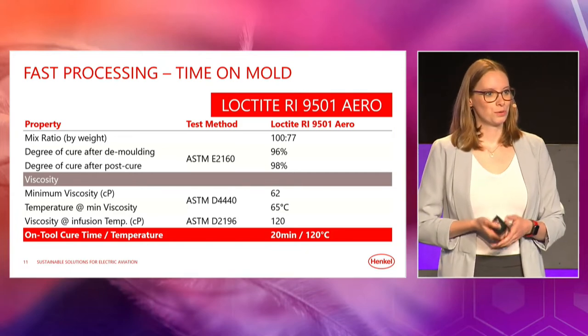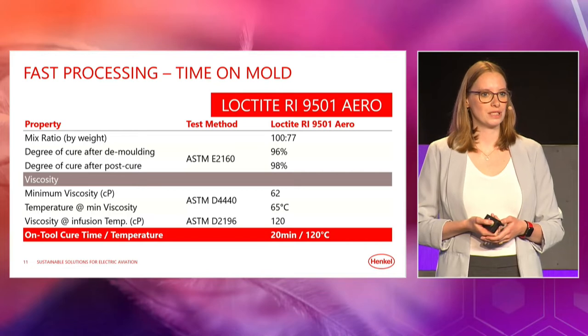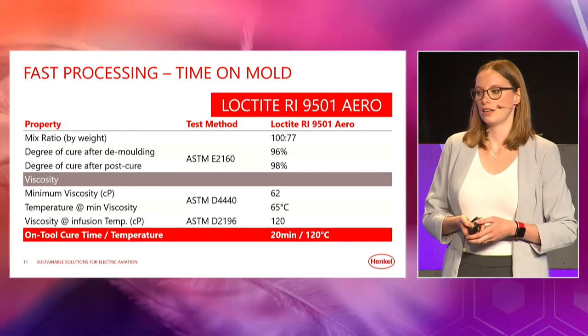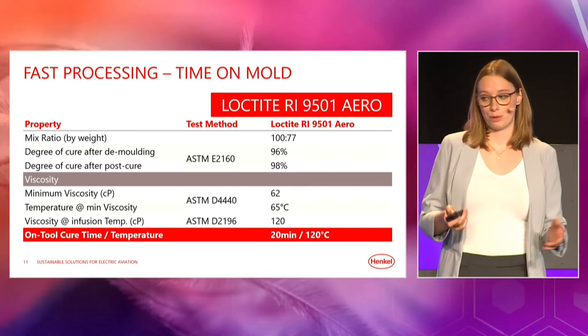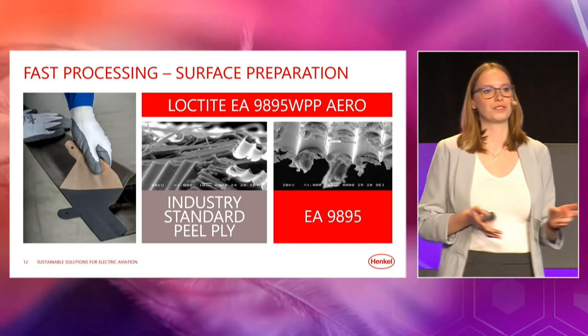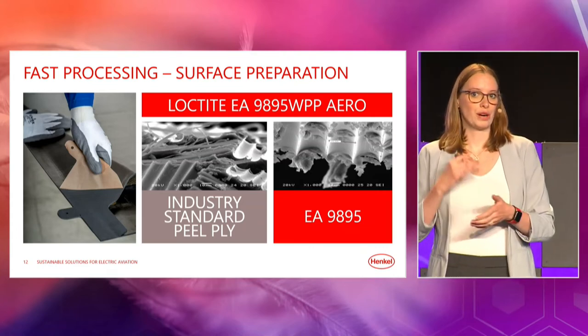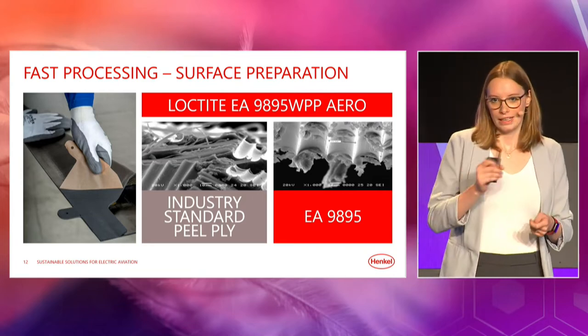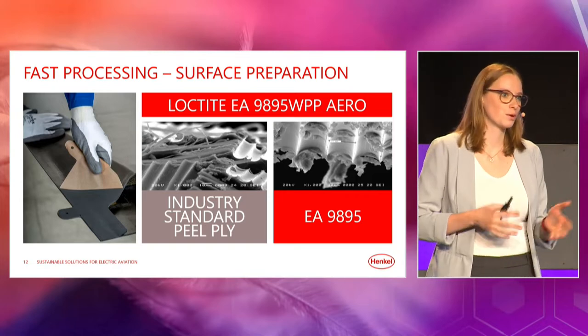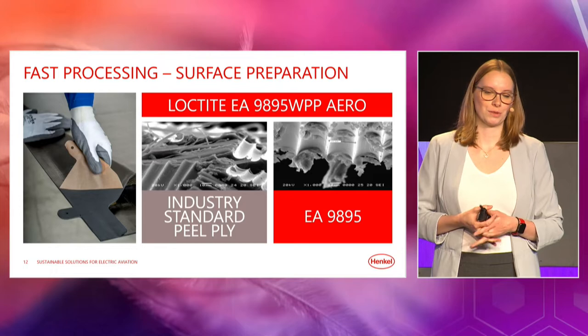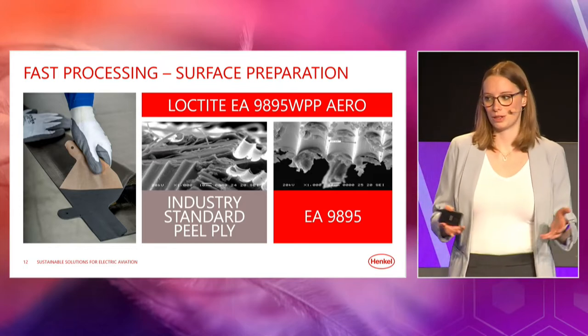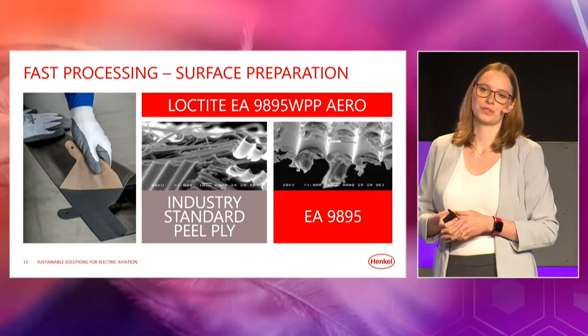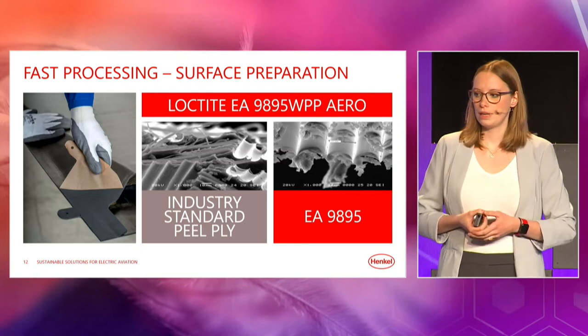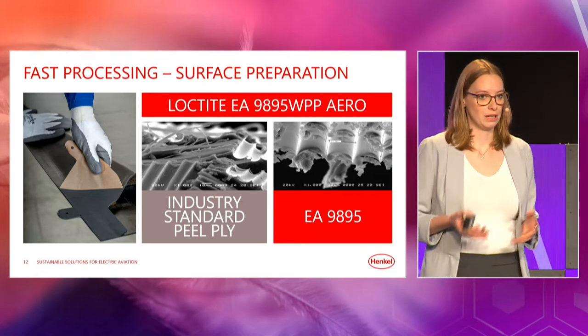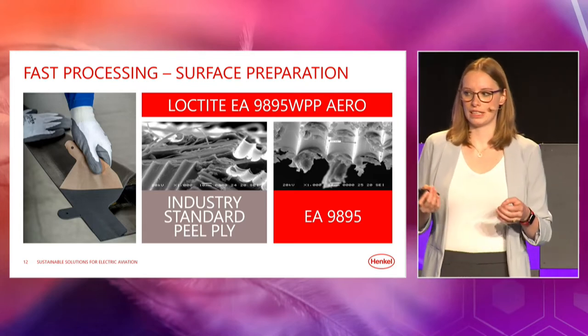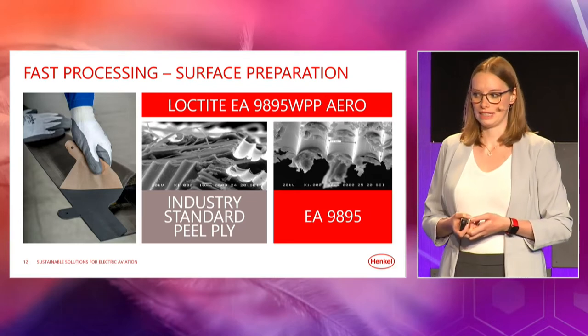As we are now able to produce composite components in RTM processes 4 to 5 times quicker than the standard process, we need to be quicker at surface preparation as well. And here we have two different processes we can use. One is abrading the surface manually, so abrasion by hand, and this of course comes with the known health and safety concerns, and it comes with the inaccuracies that a manual process includes. So we are definitely recommending using a pre-impregnated polyester or nylon peel ply, such as the Loctite EA9895 wet peel ply Aero from us. And this is really supporting the bonded joint durability afterwards.